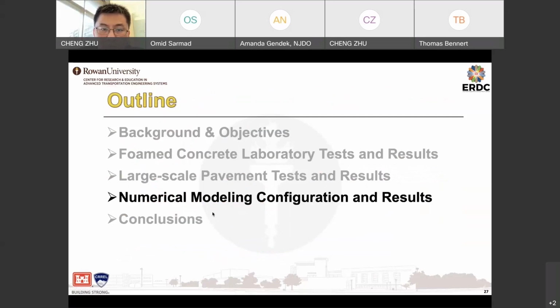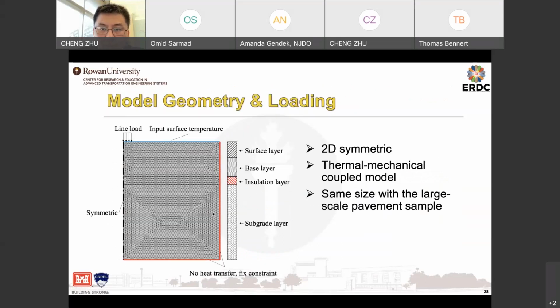Next, I want to show the numerical model that we have configured. This model was a 2D symmetric model. We consider the thermomechanical coupled process in this model, and the size is the same as the experimental sample that we did in the lab. So it includes these 4 different layers. Because it's symmetric, we only used half of the model here. On top, we also apply a line load to mimic the traffic load. The surface temperature input is the same as what we measured from the field.